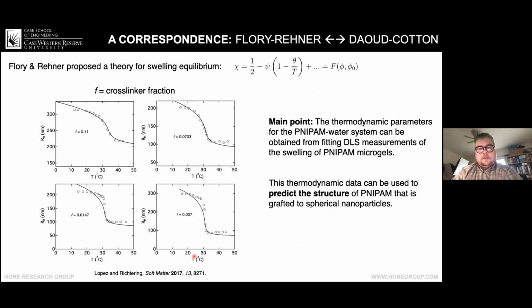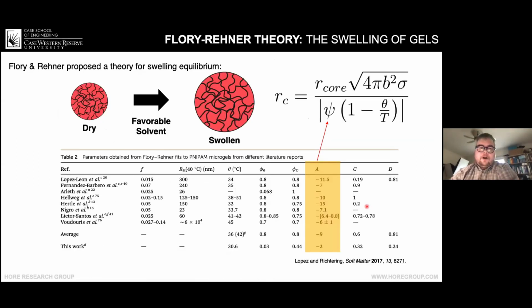And so the point is this. This is what people measure for microgels. They do DLS to get the hydrodynamic radius of the gels as a function of temperature for different cross-linking densities. And they can extract the thermodynamic properties of the PNIPAM water system that way. And our hypothesis was that we can use this thermodynamic information to predict the structure of PNIPAM. And then we arrive at a different problem.